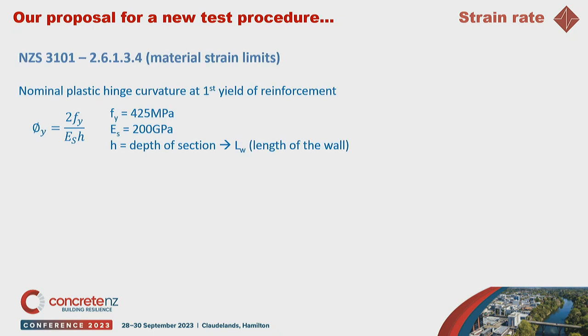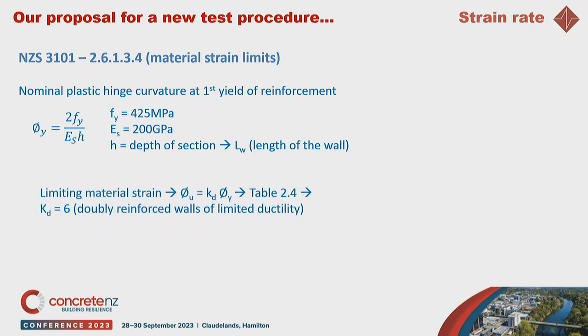And then we look at the material strain limits, because we know the time, but we have still to determine what's the epsilon u. For that, we looked at NZS 3101 and the nominal plastic hinge curve at first yield of reinforcement. And then we know that the limiting material strain is the phi y times the factor kd, which is dependent on the ductility of the structure. The more ductile structure, the higher the kd. In this case, we started with the hypothesis that we had a very stiff structure, a reinforced concrete wall, chubby, so we're not expecting a huge kd. Something like 6 is consistent with the initial hypothesis, like a doubly reinforced wall of limited ductility. And therefore, the epsilon u in this scenario is around 1%-ish.